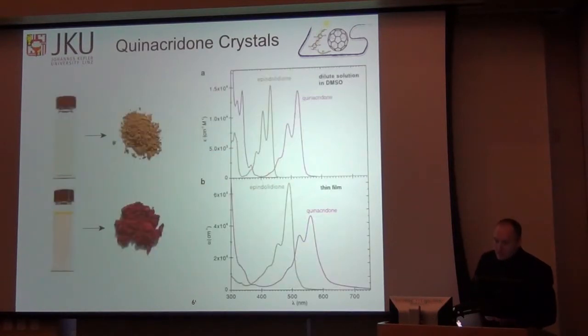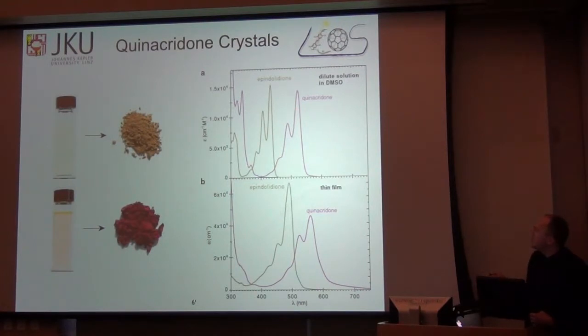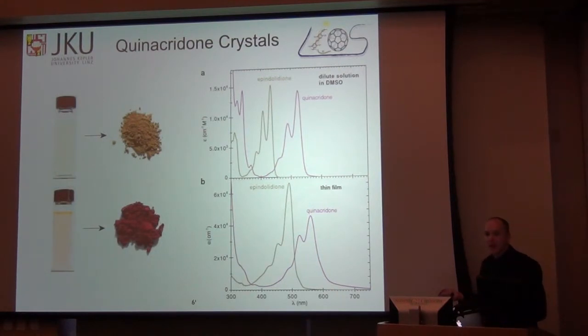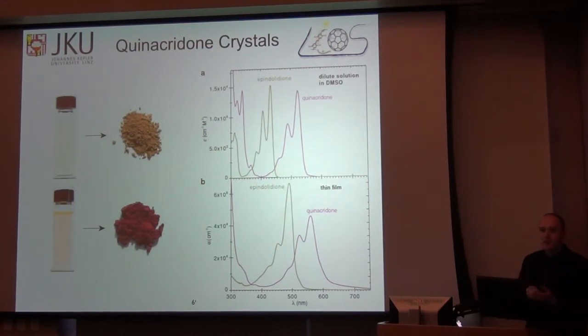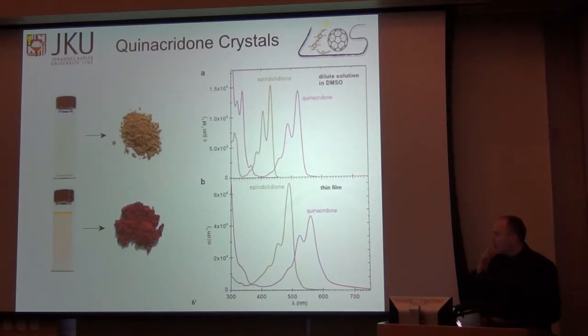And for both quinacridone and epindolidone, when you go from dilute solution, essentially monomer molecules, to crystalline thin films, you see a very strong, over 50 nanometer shift in the absorption to the red. And that's part of the definition of a pigment as opposed to a dye. A dye is a molecule that absorbs light. A pigment is a molecule that absorbs light based on its crystal structure. So if you pack it into a crystal, it absorbs light depending on the crystal structure as well. And so here we have these pigments that show a strong chromic shift when they pack into crystals.